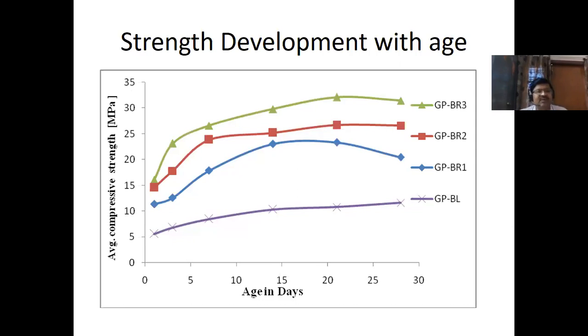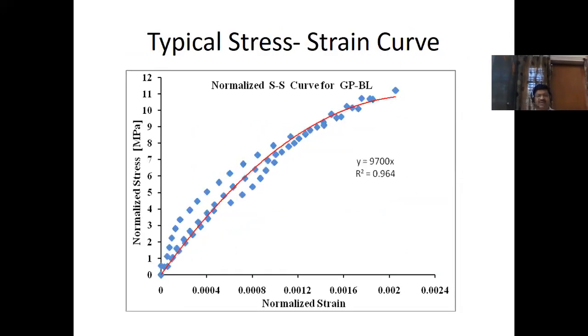And of course, we can develop strength of blocks up to 30 MPa. Rarely do we get burnt brick strength of 30 MPa, except in 2 places. One is Orissa and another is Andhra Pradesh, where the clay is very good. In the rest of the country, we will not get more than 5 to 10 MPa. So in geopolymer masonry blocks, we can get strength up to 30 MPa or more, right? And the stress-strain characteristics are almost the same as a masonry block.